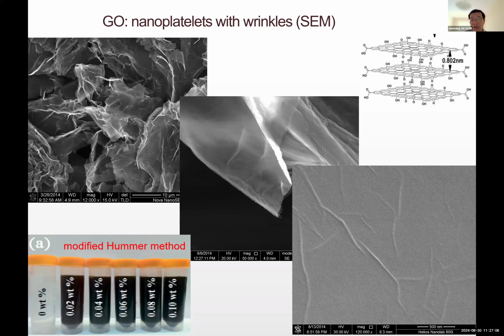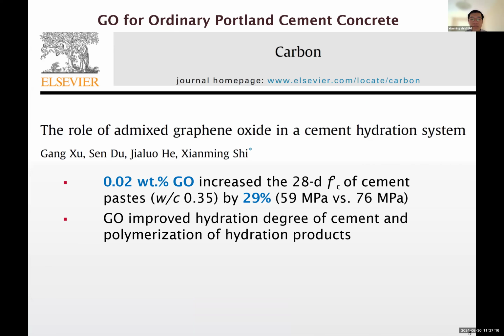These wrinkles make them feature certain types of properties that may be very desirable. Actually, wrinkles are good for us. Now, certainly my group was not the very first one studying how to use this kind of unconventional concrete admixture in concrete, but we were probably the first one to reveal some of the mechanisms of how they actually work. This is a multifunctional role. Multifunctional admixture. When graphene oxide is applied at 0.02% by weight of cement, for instance, in this case, this paper